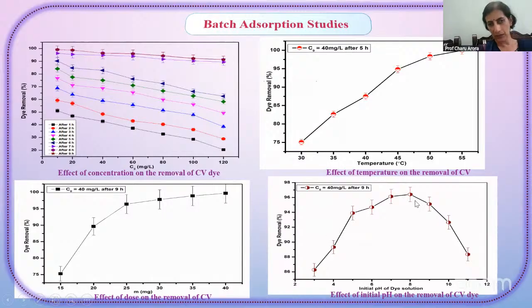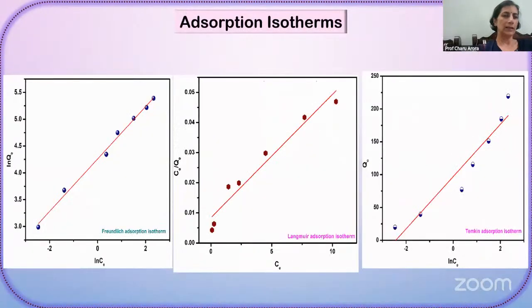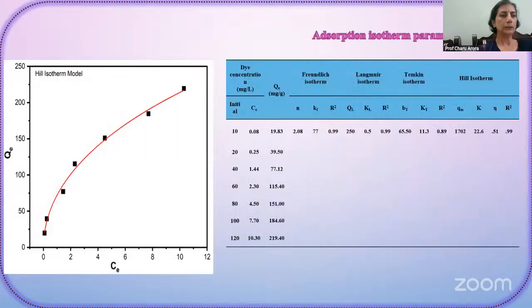Here we can see that pH 8 is the ideal pH for maximum removal of the dye. These are the adsorption isotherms, Freundlich, Langmuir, and Temkin, showing the Freundlich is the best fitted one. The non-linear Hill isotherm was also a good fit.